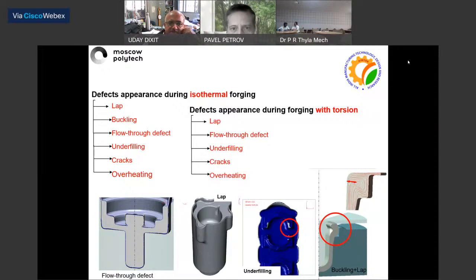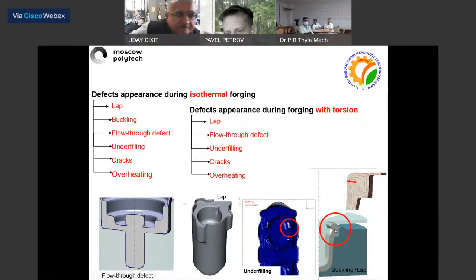At the same time, during the isothermal forging, the complexity of the forged part is very huge. And within the deformation zone, buckling could appear during, for instance, backward material flow, when the material gets in contact with the upper tool, and then the material starts to flow in the same direction as the upper tool goes. And at that stage, the probability of appearance of buckling is very high. And the manipulation with the material deformed could be performed and could be estimated due to the research on the geometrical effect, the geometry of the forged part formation at this stage.